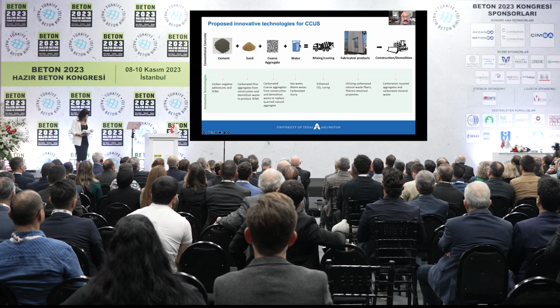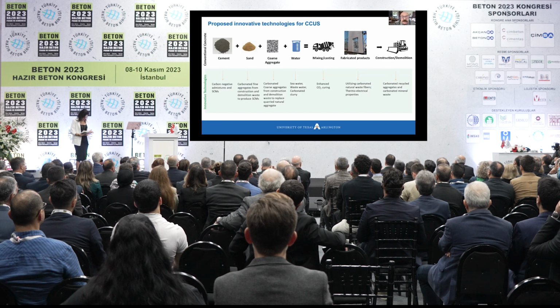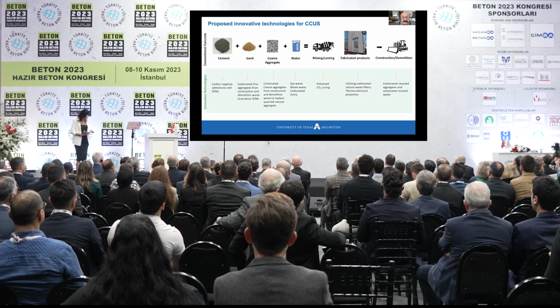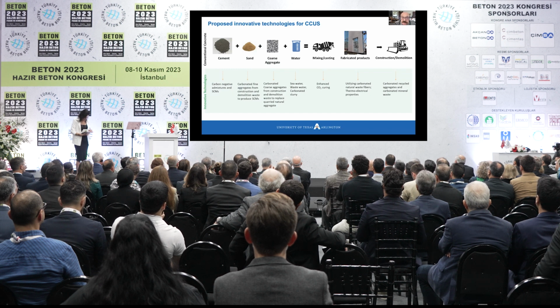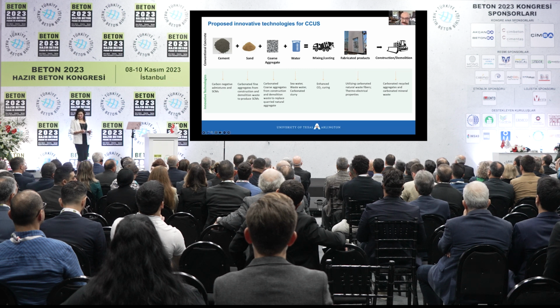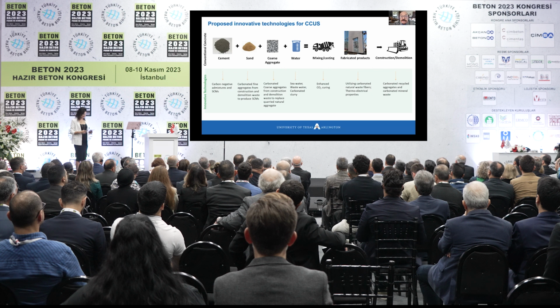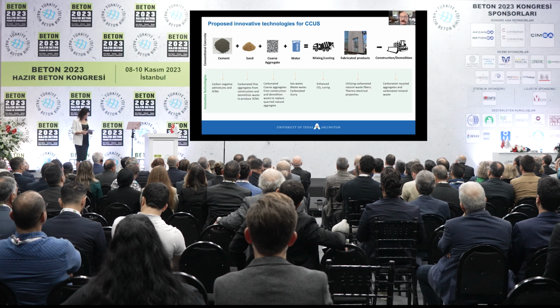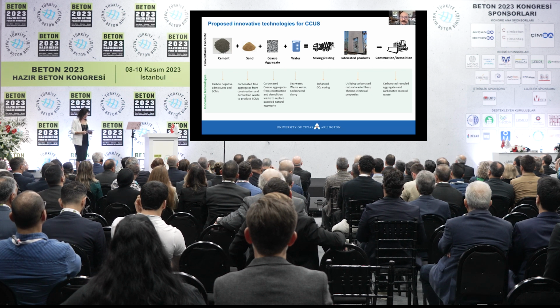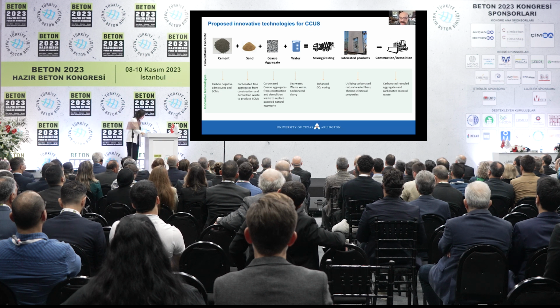Drinking water that is used in concrete amounts to 6 to 7%, and we cannot afford to use drinking water for concrete, but we can use modified seawater and municipal wastewater. During the ready-mix truck stage, we can inject CO2. However, we have to enhance CO2 curing by proper additives.